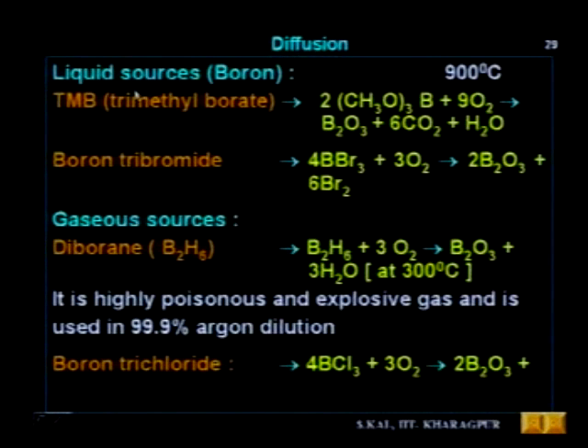Now if we look into the liquid source reactions, TMB, trimethyl borate, reacts with oxygen at 900 degrees centigrade and forms B2O3, boron trioxide, along with carbon dioxide and water, which are taken out through the exhaust pipe. This B2O3 reacts with silicon, again forming boron and silicon dioxide, and this silicon dioxide on the surface is some form of glass, and you can remove it after making the LTO in hydrofluoric acid.